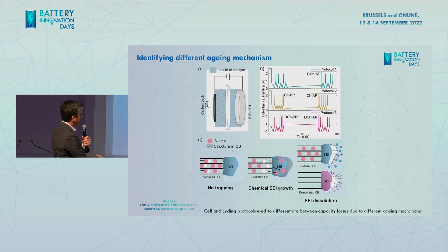And on the left, we see this phenomenon called sodium trapping. If sodium is intercalated to the electrode, that sodium can further diffuse into the current collector and trap there. So it will be much more difficult to extract it. So you need to go very low current. So with those type of schematic figures and those type of cycling protocols that you see on top right, 3 different cycling protocols, we try to understand aging in sodium-ion batteries.